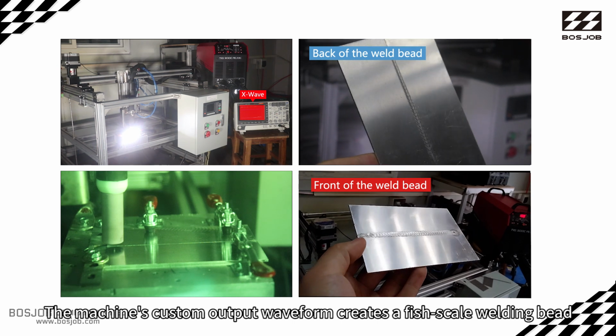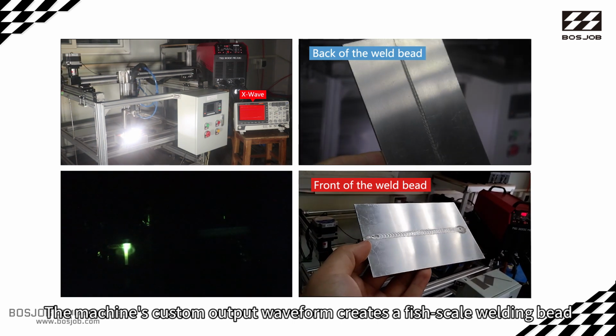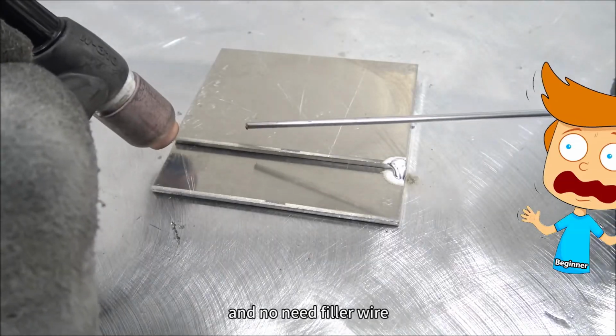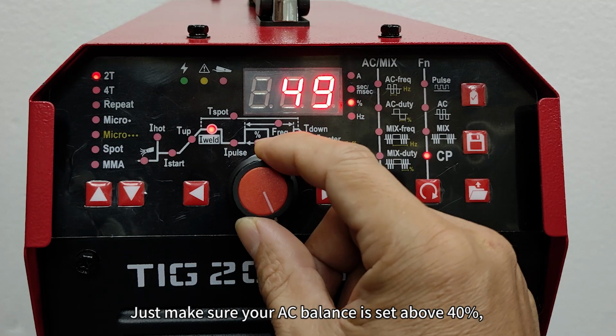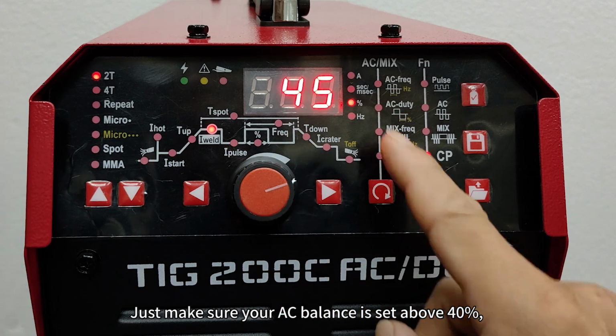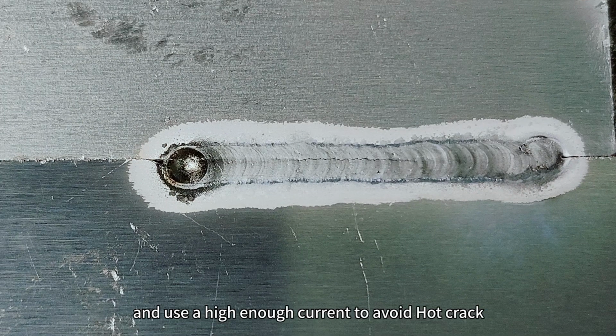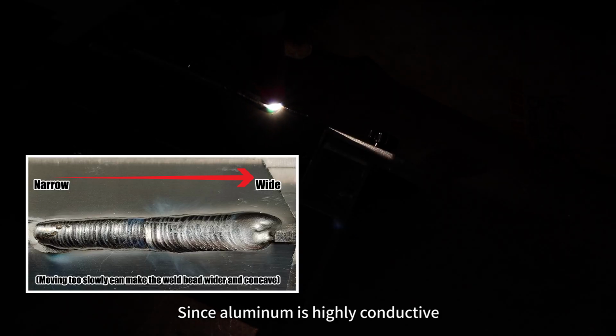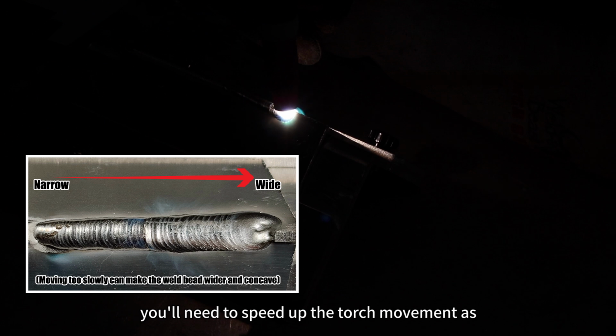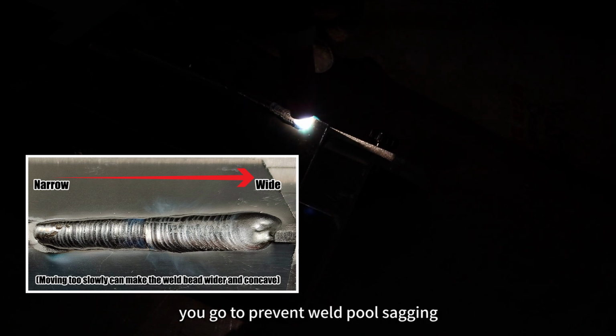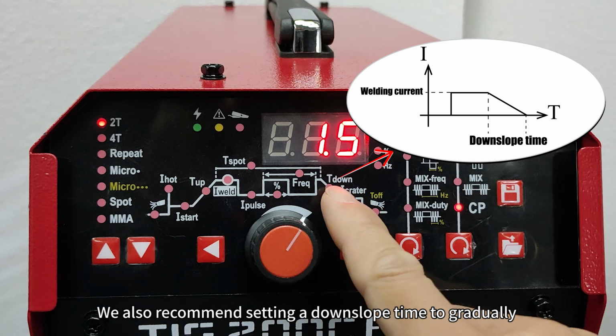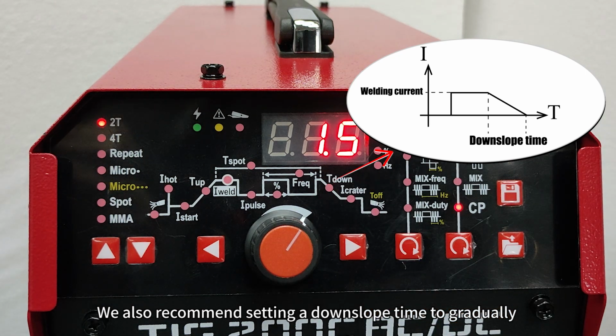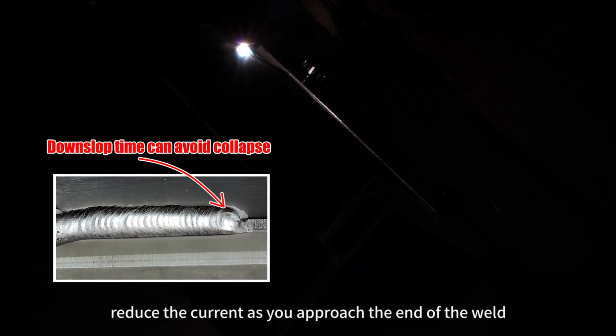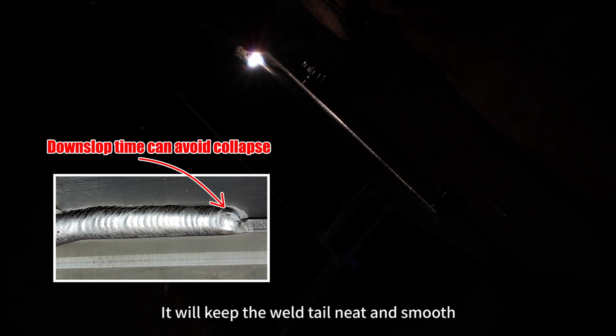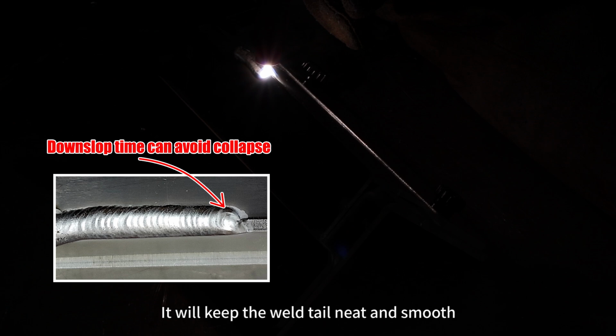The machine's custom output waveform creates a fish scale welding bead and no need for filler wire. Just make sure your AC balance is set above 40% and use a high enough current to avoid hot crack. Since aluminum is highly conductive, you will need to speed up the torch movement as you go to prevent welding pool sagging. We also recommend setting a downslope time to gradually reduce the current as you approach the end of the weld. It will keep the weld tail neat and smooth.